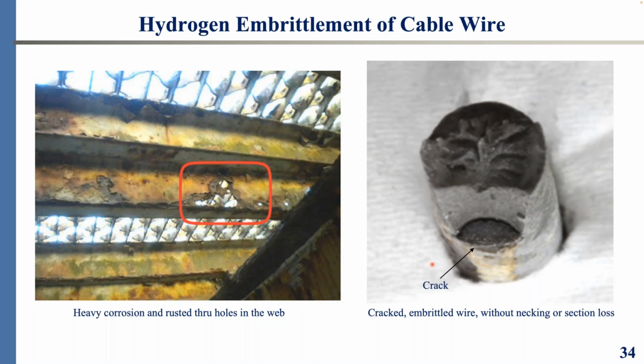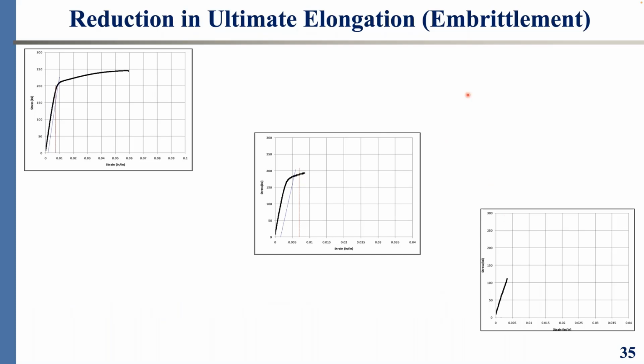So you see here the impactful effect of cracking and embrittlement that go hand in hand from that brand new wire over time that would decrease in ultimate elongation up until it reaches this very low level or even lower. Had we left this particular wire in the bridge cable, it would be getting broken very soon because it has very low ultimate elongation, and with further crack growth, this ultimate elongation will be further lower and lower and lower up until the wire breaks. And actually, I mentioned the energy under the stress strain curve. You can imagine the level of energy that is included here under this wire. That's very healthy, and this is much lower, of course, level of energy, but over here is a sliver of the energy on that previous one.